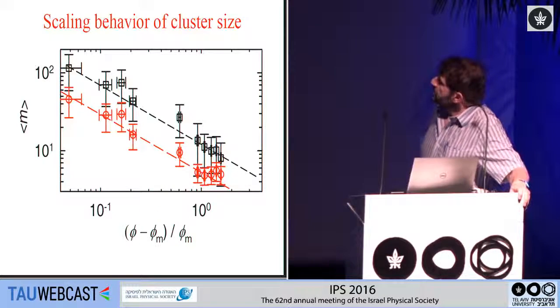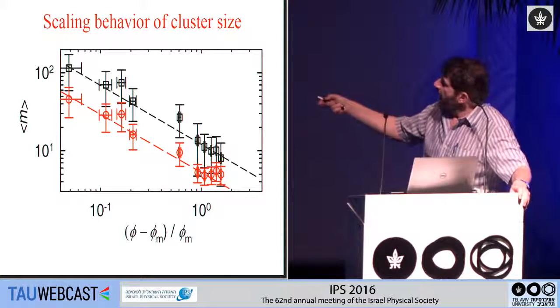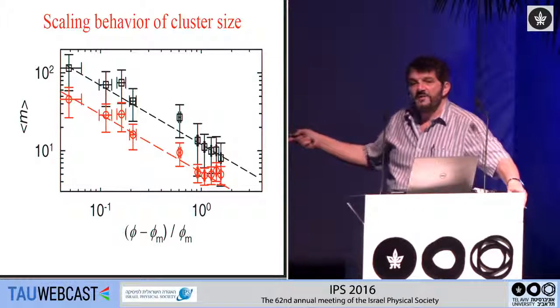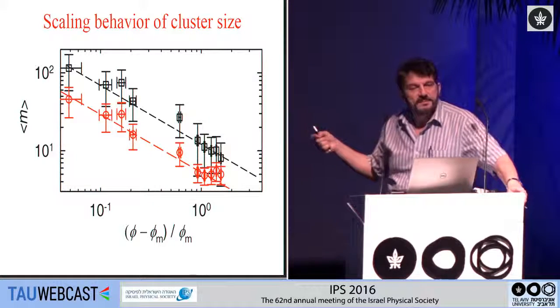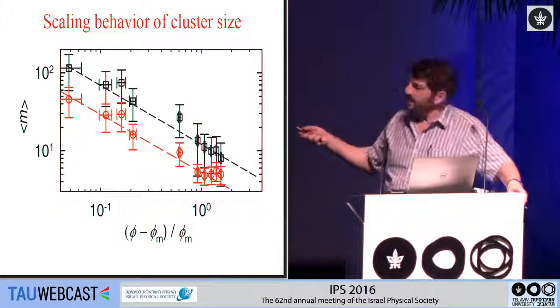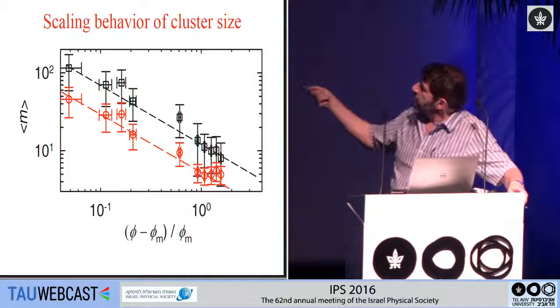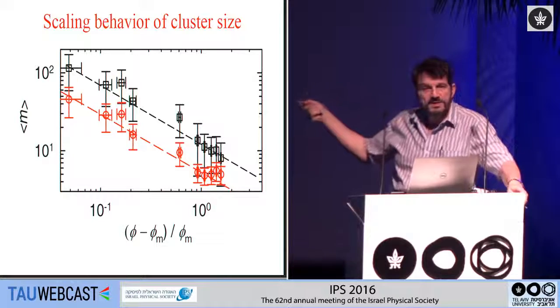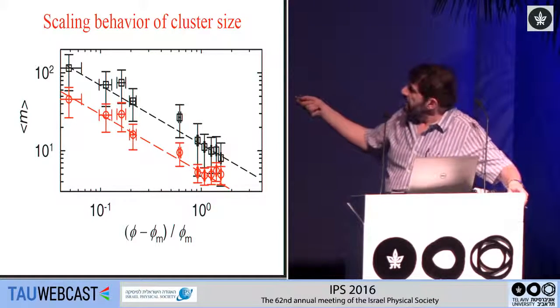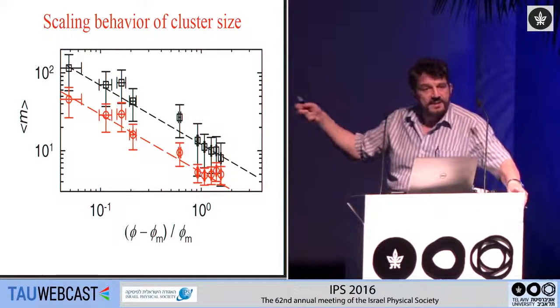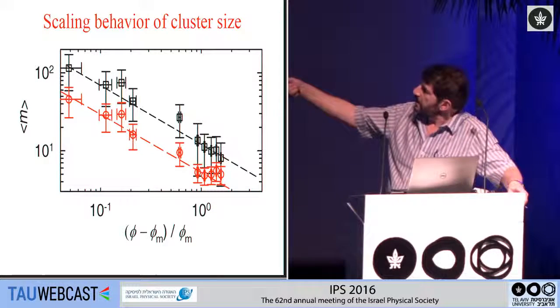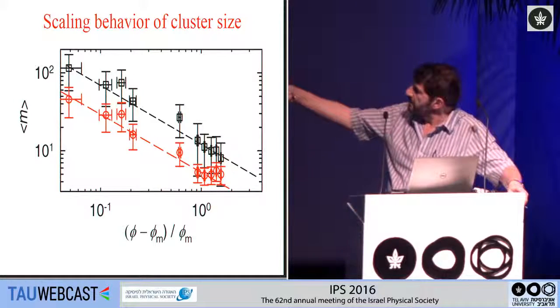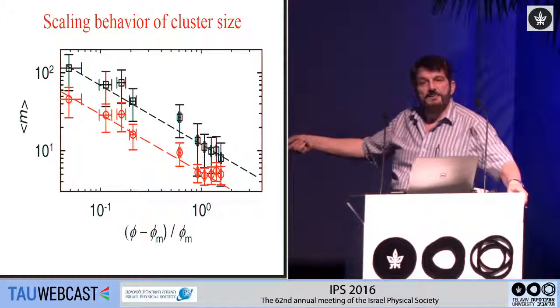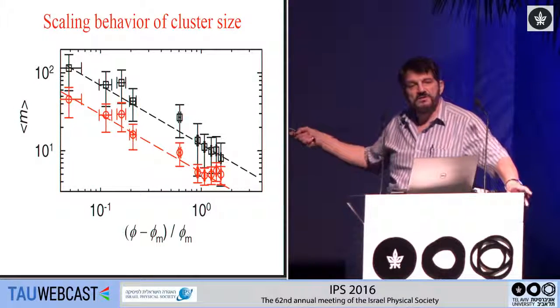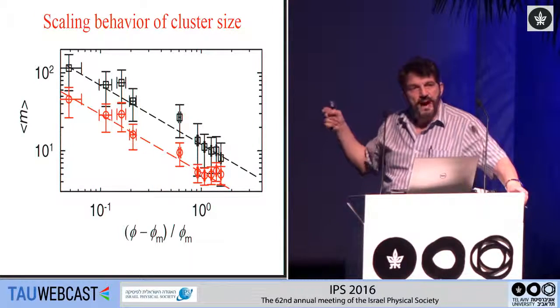However, what's quite interesting is that if you plot the mass as a function of this normalized distance from the melting, you see a power law distribution. So these are the average mass and the mass of the largest cluster. You see that as they approach, they exhibit this power law distribution. I'm plotting on a log-log plot the mass as a function of the normalized separation from melting. And you see a power law distribution.